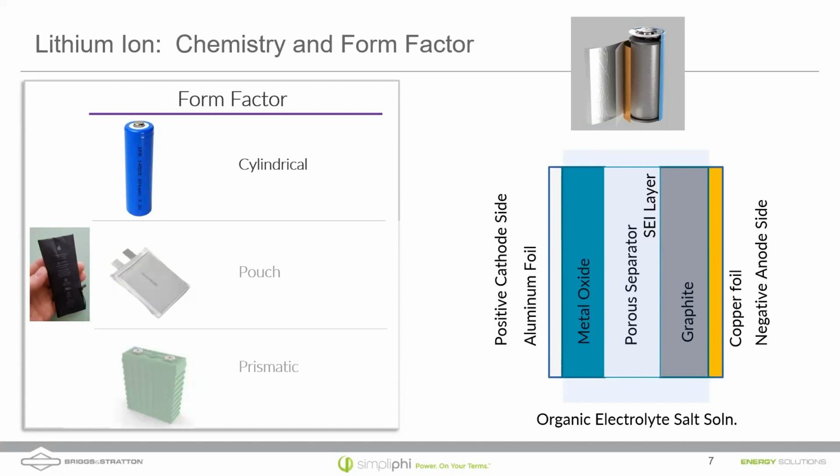And so at low temperatures, the lithium can end up getting stuck outside the graphite and even forming solid lithium deposits, where you basically are creating lithium metal and having the lithium ions in the electrolyte solution form what are called dendrites, and that word means branches. So the growth of lithium on the graphite layer can, if you do this over time, build up to the point where it could even short circuit a lithium battery.